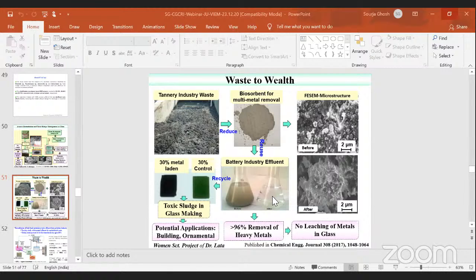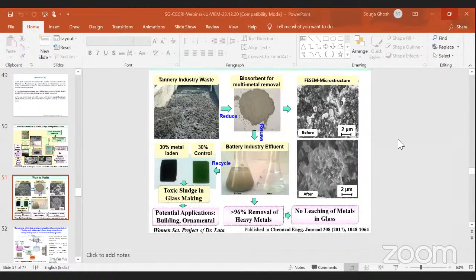After removal of metal, there were four types of heavy metal found, that is cobalt, lead, nickel and cadmium. These metals were completely removed, and 96% removal was achieved. Then this metal-loaded sludge, this is the microstructure. This sludge was used in immobilizing in the glass matrix. So up to 30% of metal-laden sludge could be incorporated into the glass matrix. While studying the leaching, no leaching of the heavy metals was found during the experimental region of the study. And as this glass also contains color, it can be used for building and ornamental applications. And this is the technology for immobilizing toxic metal containing waste into safe glass.